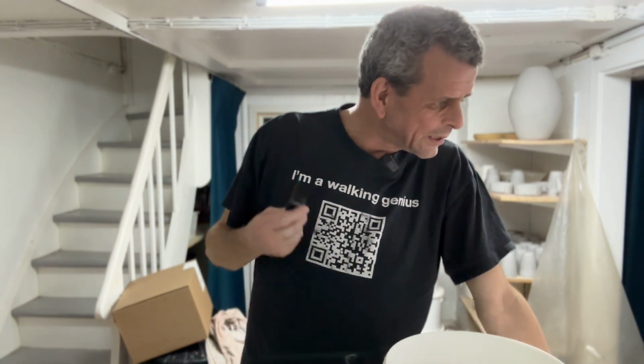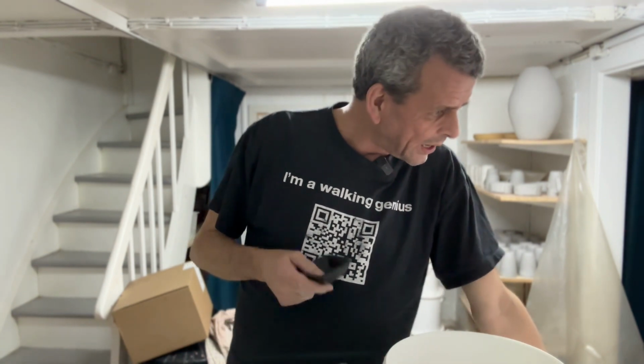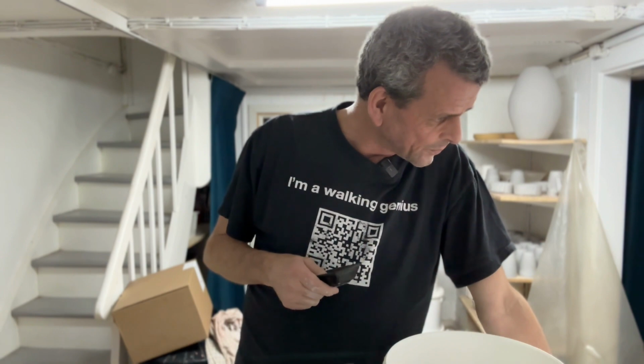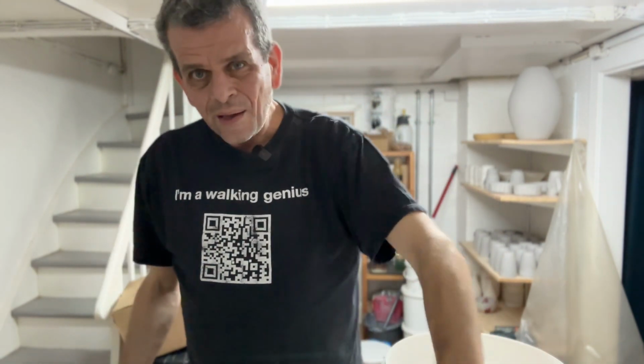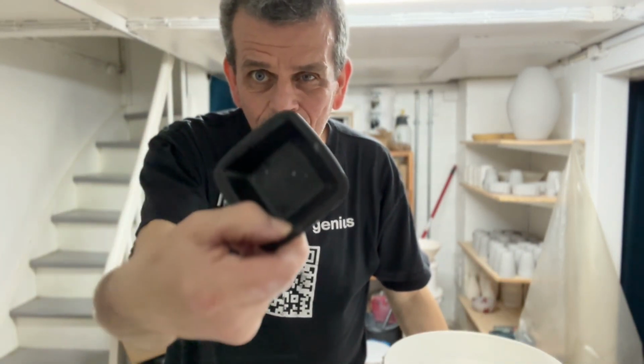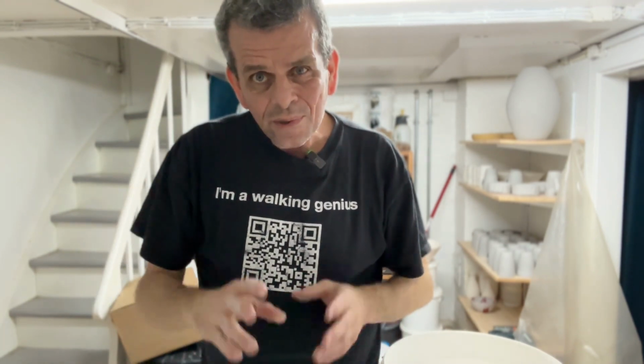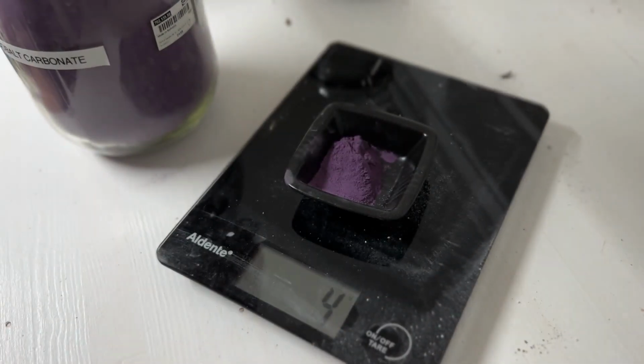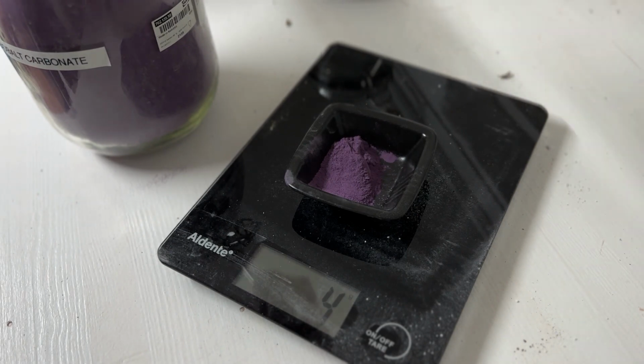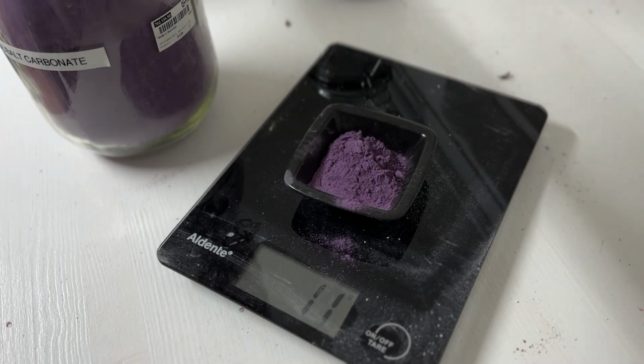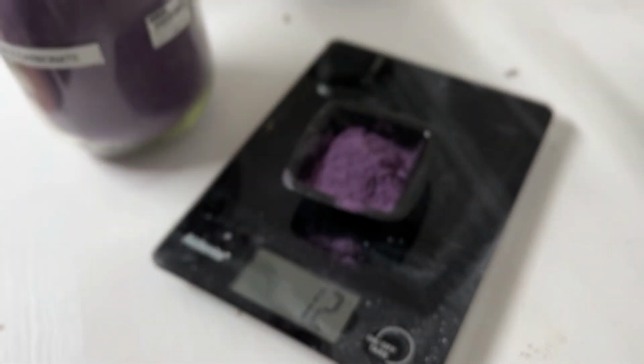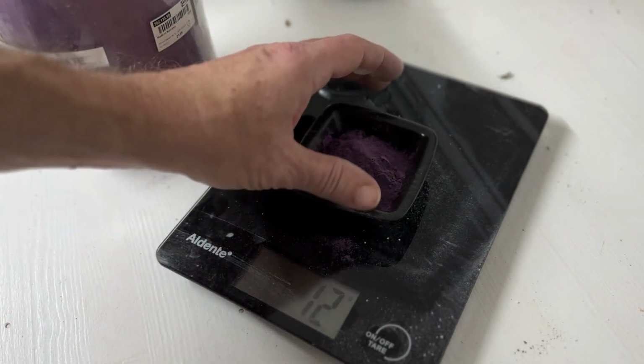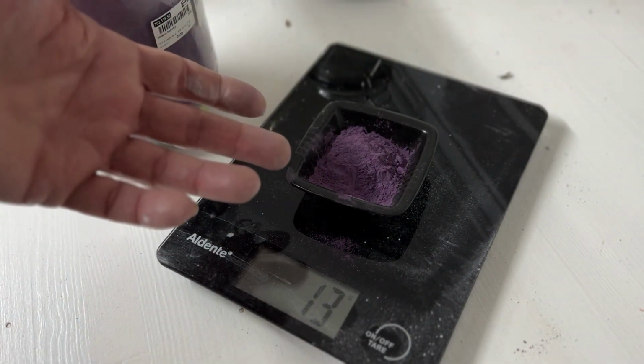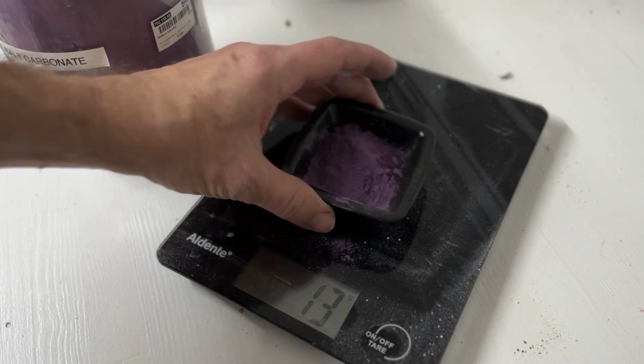I guesstimated that we need 0.5% of the black stain and only 0.3% of the cobalt carbonate. So that's 20 gram and 12 gram. This bucket is way too big to measure that. So instead I have this very small bowl that I would use instead. For very small amounts, that's much easier to do. So 12 grams, it's not that much, considering I'm putting it into 4 kilos of dry materials, but it is a very strong colorant.